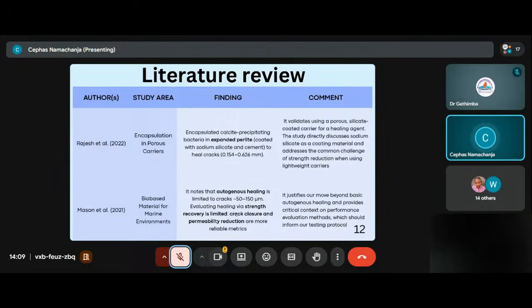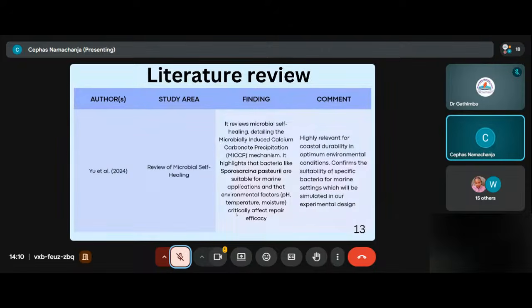Okay, for our literature review, the first literature review, the study area was the encapsulation in porous carriers. Now, in this, we found out that they used expanded perlites as their carrier, which affected the compressive strength of concrete when it was inside the concrete matrix. So, as a change, we are going to use a different carrier, which is the silica gel granules. For the second one, which was the bio-based material for marine environments, their study evaluated healing mainly through observing crack closure and permeability. And for us, we're going to evaluate the healing through strength recovered. And then the third one was the review of the microbial self-healing.